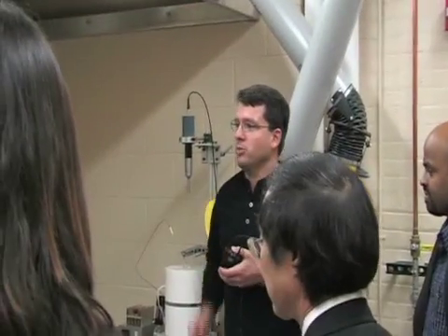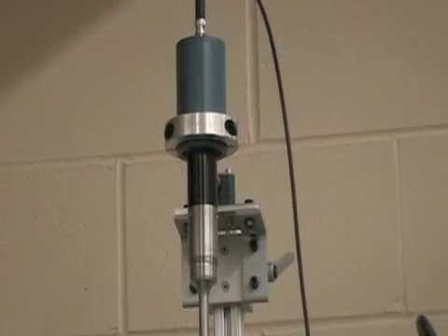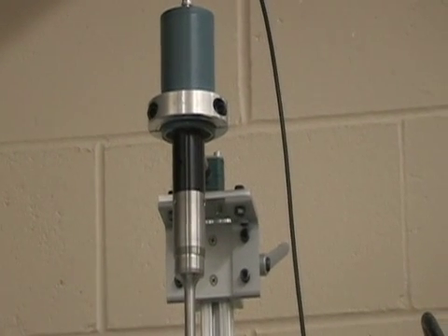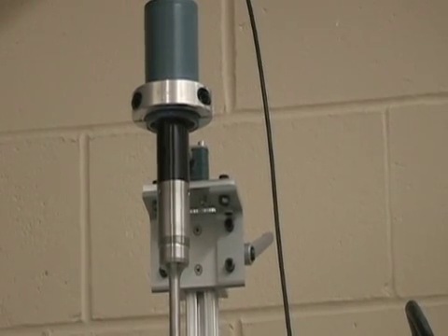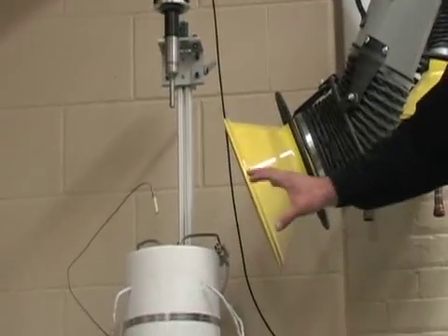So in here we work on metal matrix nanocomposites. So we're taking lightweight aluminum and magnesium alloys and pure metals and then adding nano silicon carbide or other ceramics into them to create a strong composite material. And recently we found that we can double the strength of the matrix material with just a 1% volume addition of the ceramic nanoparticles. And when you compare that to conventional metal matrix composites where you put in, say, 20% of 10 micron or so size silicon carbide pieces, we get better strength enhancement, but we also don't pay a lot of the penalties that you typically see with metal matrix composites.